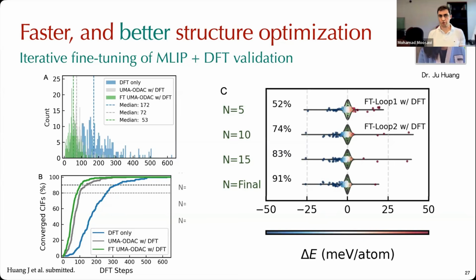But it's not just faster or more efficient, it's actually better, because if you look at the energetics of the crystal structure at the end of the optimization, you see that in 91% of cases, you end up with a crystal structure that has a lower energy. Each dot shows one crystal structure going through this iterative fine-tuning and DFT optimization. Then we compare the energy of the structure to one that is fully DFT optimized. If the energy is lower, we found a better optimum. And you can see that in almost all cases, we got it better. And remarkably, with only 15 steps of DFT, you get 83% of materials finding a better solution.